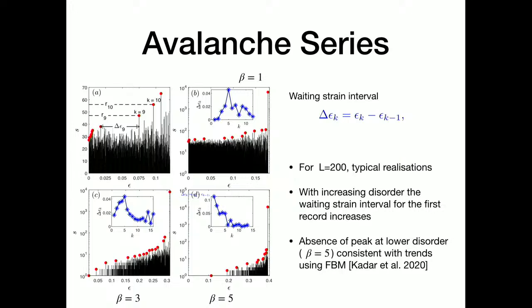But if you look at beta equal to 1, which is the intermediate disorder, you see that the first record is made instantaneously as soon as the loading starts, and then the next record is also not too far away, but then the interval slowly starts increasing, and then you have a period where nothing happens, which is the longest period of wait, and then slowly it starts again becoming faster before final failure. So that is what is reflected here.